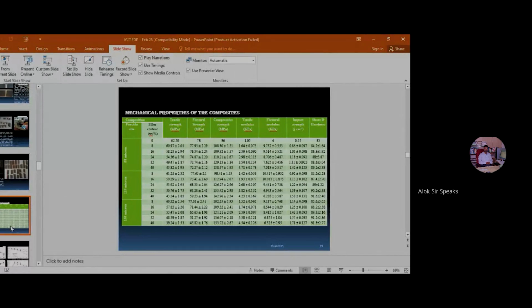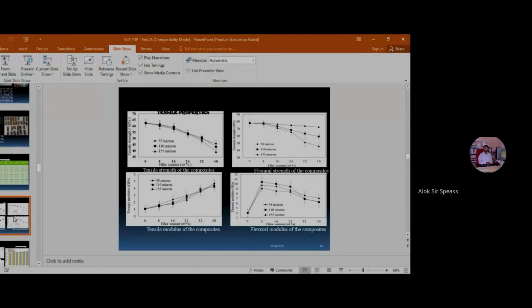Same also in the case of tensile strength, flexural strength, impact strength, and their moduli, because the size and shape have a very prominent role in impacting the strength property values. Now these are the variations of the different strength properties in terms of a graphical chart. You can see that the composites with 55 micron, 110 micron, and 155 micron particulates are different. The properties are different, although they appear the same up to a certain point. After a filler content of more than 16%, they are differing. So depending on what flexural strength, tensile strength, or modulus you need for a particular application, accordingly you can tailor make the composite.